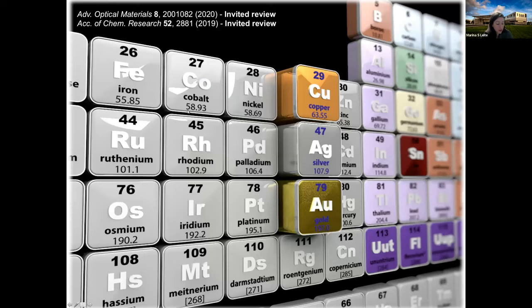Now, the work that I'm going to share with you today is going to be heavily based on these coinage metals: copper, silver, and gold. And the reasons for that are the following. First of all, these three metals have a somewhat similar band structure, and I'll tell a little bit more about that in a second. They're quite similar, in fact. They're all FCC, right? There has been an enormous amount of work related to nanophotonics based on silver. This is a material that works extremely well for plasmonics. And they do have, at least for silver and gold, nearly identical lattice spacing.